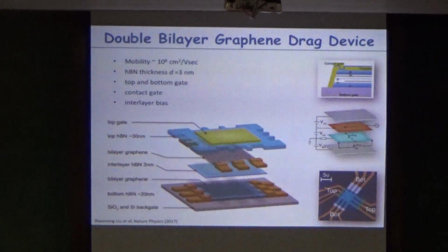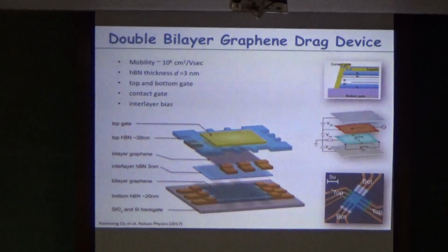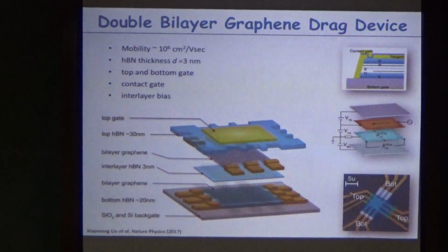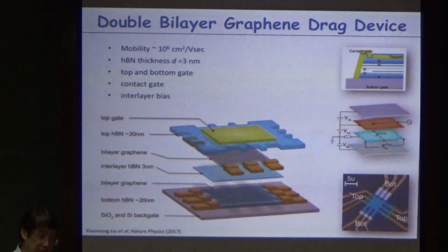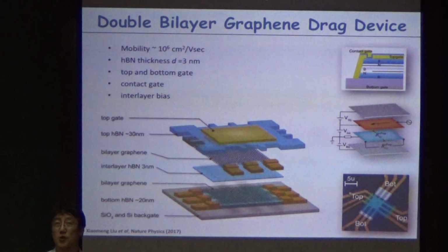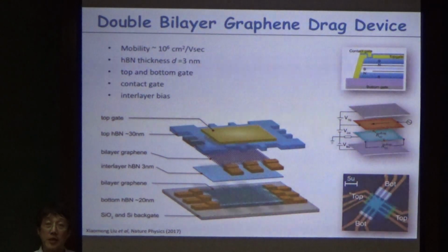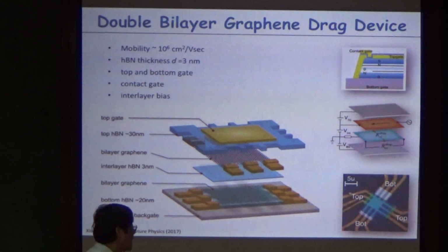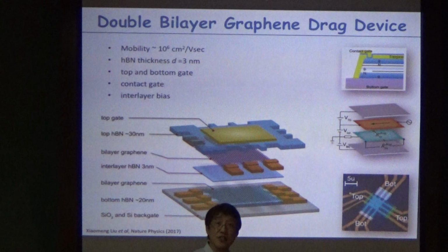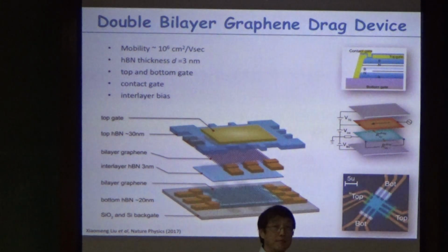Compared with this, in the gallium arsenide heterostructures, because of the growth issues, the two layers are about 10 nanometers away. In graphene, we can put them extremely close by, without even tunneling, right? Which means the binding energy of the electron-hole pairs that I just mentioned becomes even larger, so the experiments one can realize become really robust.